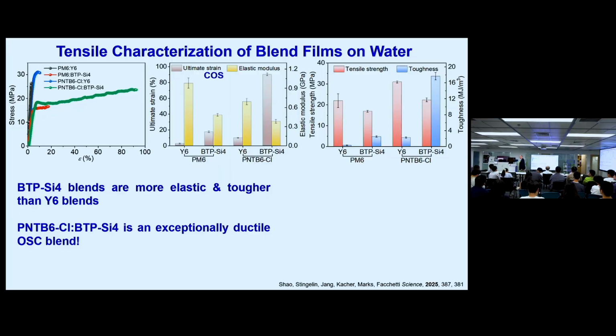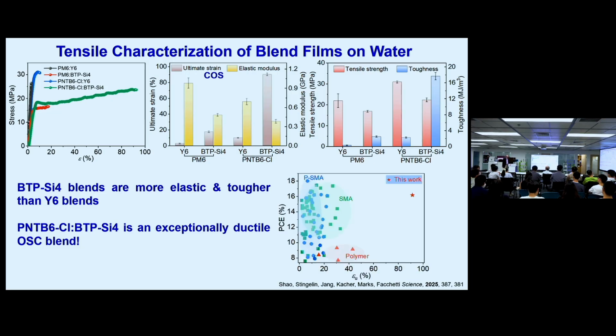And so let's just finish up now. So one way to plot it is, this is PCE. This is a map of every stretchable or unstretchable solar cell material that we could find in the literature. So SMA means small molecule acceptor, polymer means all polymer solar cell for donor and acceptor. And this is PCE, and then how much you can stretch them before they break. And you notice in the upper right-hand corner is the material I showed you, which has the silicon substituted acceptor. So essentially, we've added an acceptor into this blend, which plasticizes the material, makes it more flexible.